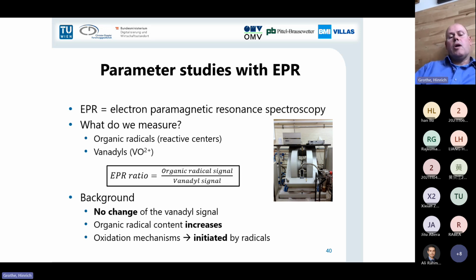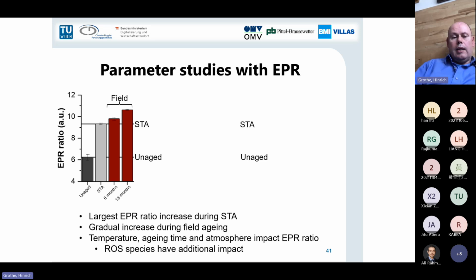So just to give you an example, with the EPR we determine the so-called EPR ratio. That means we record the organic radicals and set that into relationship to the vanadyl signal. Why have we chosen the vanadyl? Because this is not changing during aging. So this is our standard, if you want.